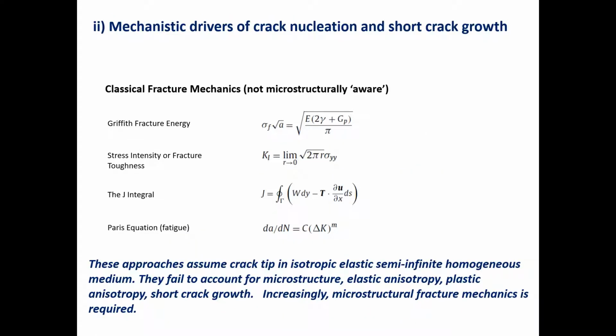The drivers for crack growth developed in the past, the classical ones of course include Griffith, which was the balance of energy related to the new surface generation. The surface energy is given there as gamma, extended to incorporate plastic work. In parallel, the stress intensity approach, which has been used very successfully, of course, for conventional cracks and crack growth, but is very much with the limitation that the material is assumed to be elastic. In general, it's also isotropic.